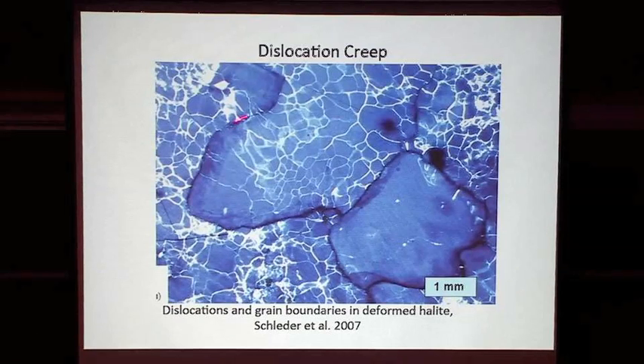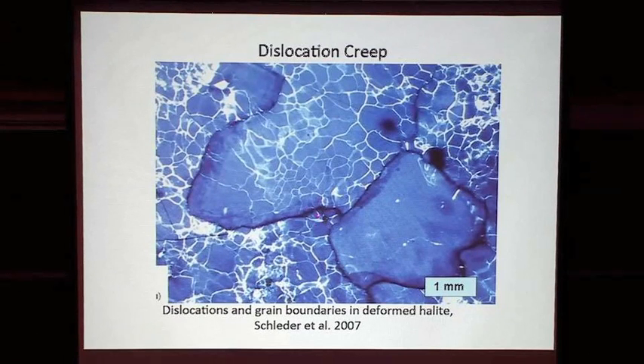So these are individual halite grains deformed in dislocation creep, and the light things are the dislocations. And what you can see is that the dislocations are in fact sort of junior grain boundaries, and a term for these is that they're becoming subgrain boundaries. And when enough rotation and deformation takes place on them, then they actually convert to grain boundaries.